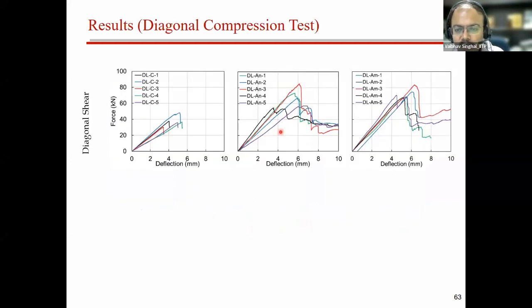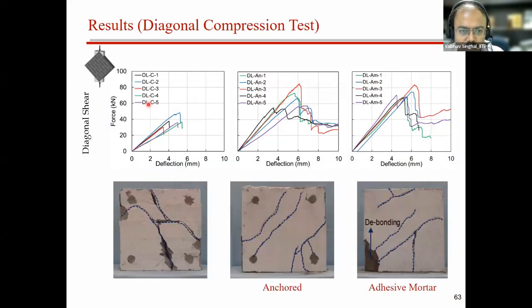Now, these are the results for the diagonal compression test. Again, the diagonal compression test also showed quite similar results for both techniques, anchor and adhesive mortar. And this is how the failure was seen. With the adhesive mortar, as you can see at the bottom, debonding was observed. The control specimen failed suddenly, with complete disintegration of the specimen when tested without any strengthening.